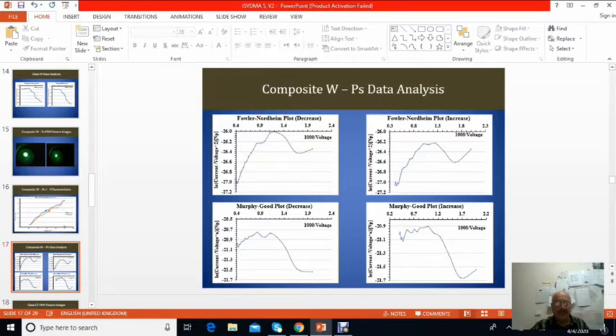The composite tungsten polystyrene data analysis. Here is the Fowler-Nordheim plot. This is the Murphy-Good plot. This is the decrease when the emission current went down, and then when it is increased. So this will prove to be very important to analyze. Now, it is not a well-known characteristic or analyzed, but we are working very hard with an international team to analyze this very important